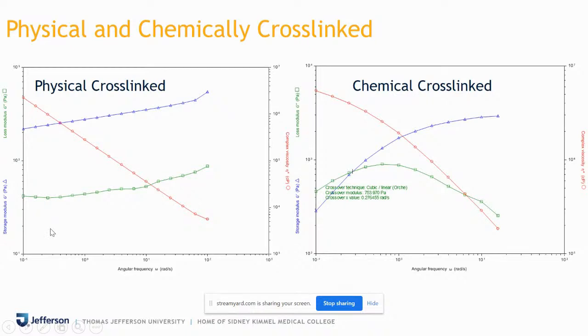First point. Second thing is, if you change the pH or the chemistry of these physically cross-linked systems, the frequency sweep experiments will not change. Whereas some chemically cross-linked systems are actually sensitive to pH variation or chemistry variations, because they are cross-linked with some kind of a cross-linker. So you need some kind of a reaction to happen to tie the polymer pieces together to create a hydrogel.